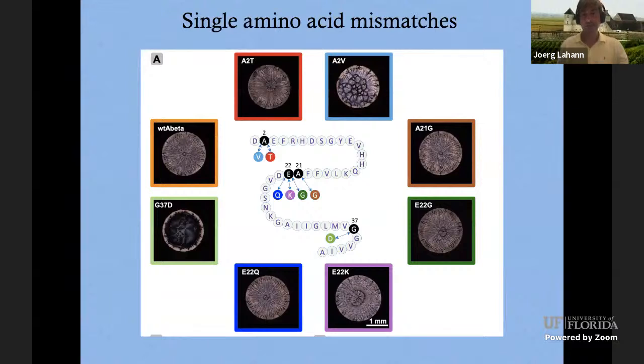Okay, so this is the first thing, single amino acid mismatch. This is the peptide. You have the sequence here, and then we go in and say, okay, we take the second amino acid and we replace it with either a V or a T. So we're basically looking at those different structures, and these are the images we collect. And you'd say, okay, maybe they are quite different in some cases, but they're very similar in others, right? And then of course you also have to consider variability within a single droplet system. And so now we're basically running that through our neural network.